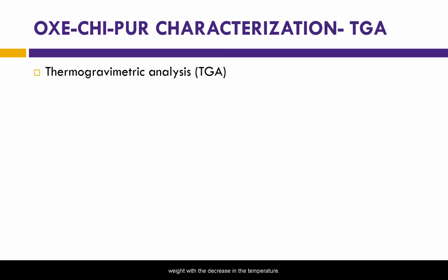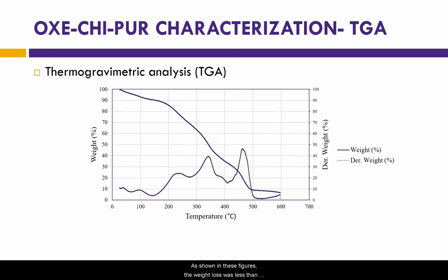This slide presents the thermogravimetric analysis of the final material. TGA results present the change both in weight and derivative weight with the increase in temperature. As shown in these figures, the weight loss was less than 10% at around 163 degrees C. This initial weight loss can be related to evaporation of residual methanol used for washing and isolation of oxetane-substituted chitosan. Based on this result, it can be concluded that the produced self-healing polymer is suitable for use during asphalt mixture processing. Furthermore, a 50% weight loss was observed at around 350 degrees C.